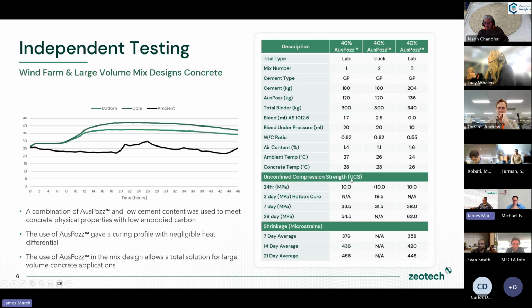So if I go right down to look at the strength gain, we're looking at pretty much equivalent. In fact, we didn't have a standard GP here because we just put AusPozz in all three. But you see here, the strength was matching what we needed. 30 MPa was the target, and we're up at 28 days, 50, 60 MPa. And also shrinkage, some very good shrinkage results, even less than 500 here. But the key here was to try and get the temperature differential down in this work.